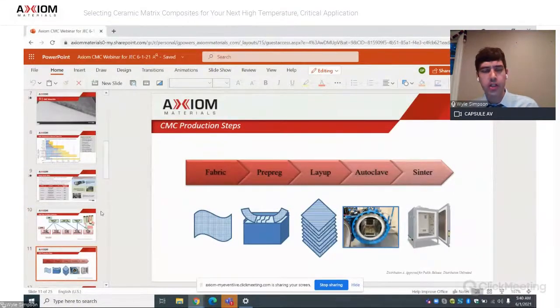So CMC production follows sort of the same routes that composite production does. Composite prepreg. You have a fabric, you coat it with our solution, lay it up, autoclave cure is what we'd recommend, and then sinter it at high temperatures. That's the one difference between sort of processing those standard polymer matrix composites versus these high temperature CMCs. There's a sintering step that's required after autoclave cure.